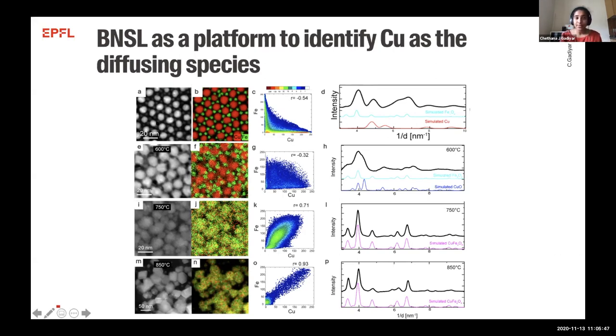So what we did is we started annealing this assembly at different temperatures. Already at 600 degrees Celsius, we were able to see that there is an interdiffusion of the copper and iron species taking place. At 750 degrees Celsius, we already had copper iron oxide nanocrystals formed. And at 850 degrees Celsius, we were seeing sintering of these copper iron oxide samples, forming large particles of copper iron oxide. So from this study, we concluded that above 750 degrees Celsius, we were having large particles of copper iron oxide, and it was difficult to control the shape of these particles.